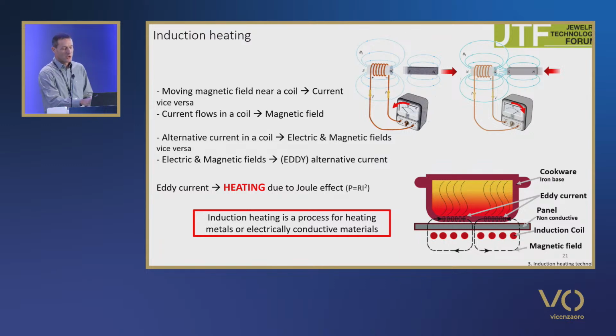So, as shown on the induction hob, the induction coil in the induction hob creates a magnetic field. The cookware is made of iron materials, sensitive to the induction field, so an eddy current is created, and the heating effect appears. So thanks to this eddy current, it is possible to heat a conductive piece without contact.